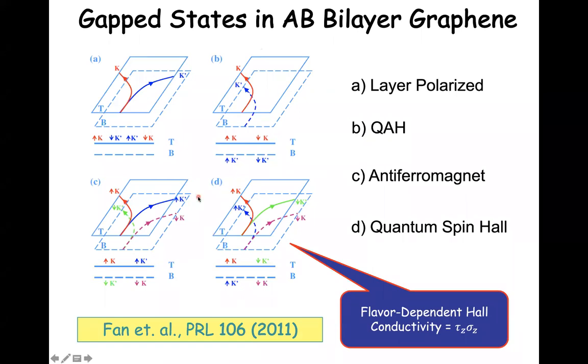Now I have to complicate the story a little bit and admit that there are 4 groups of such states, distinguished by the valley I was speaking about, which of the 2 momentum regions the states are located near. And also there are 2 spin states labeled here as spin up and spin down. And those can, as indicated in this cartoon, be layer polarized. Each of them can be layer polarized more or less separately. And so for example, state B in this cartoon is a state in which, maybe I should do this one first.